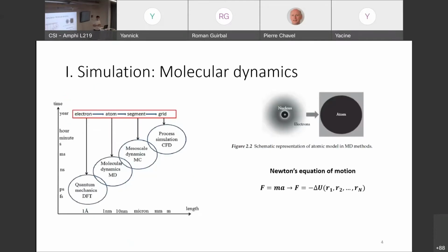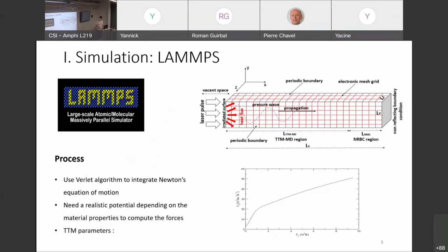So we'll first present the simulations we'll do. To simulate the laser-metal interaction, we are using molecular dynamics. So it consists in considering the atoms of the material and applying Newton's equation of motion on each of these atoms in a way to understand the behavior of the material. To do so, we use the software LAMMPS, which stands for Large-scale Atomic/Molecular Massively Parallel Simulator. And this software uses the Verlet algorithm to integrate Newton's equation of motion, as we said before, and to simulate the laser pulse, we have to put a TTM model, which is a two-temperature model, so which simulates the equilibrium between the electron temperature and the lattice temperature.